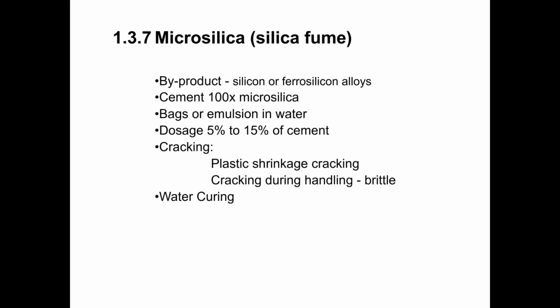Generally, for silica fume, we can have a dosage of anywhere from 5 to 10%, or 5 to 15% of the cement content. So I think your book gives a little bit lower number than that. On page 1.13, the third paragraph down from the top, it says between 5 and 10%. We can see silica fume used at higher percentages. So I would change that to 15% because you can definitely use it above 10%.